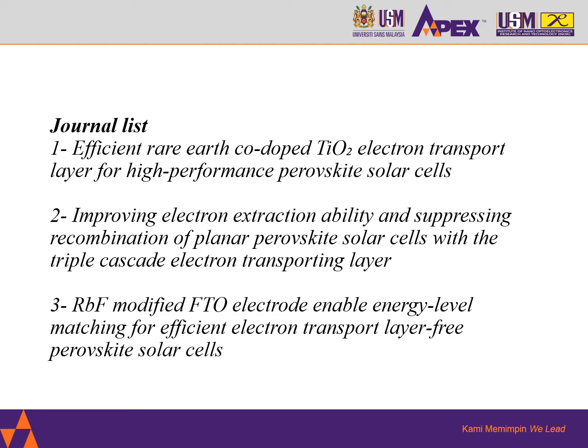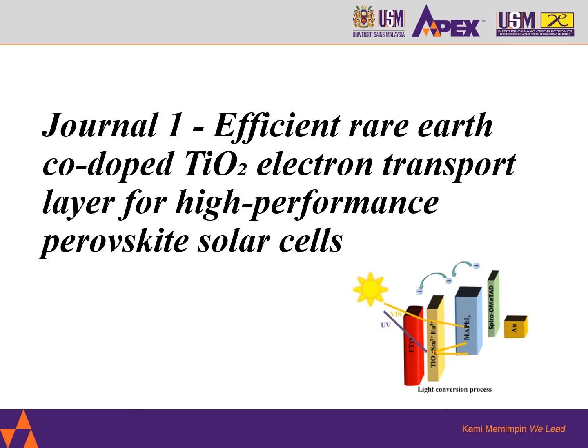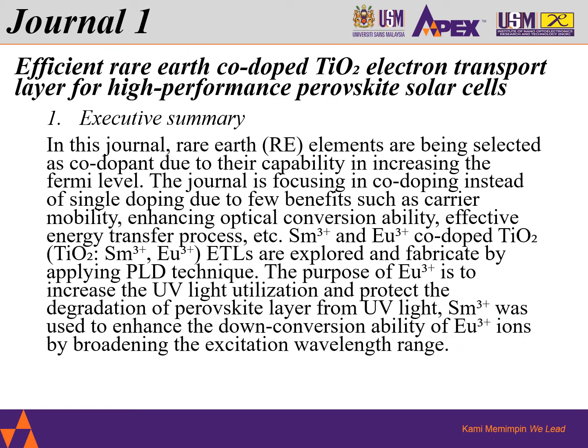For journal 1, this is the structure of how they carried out the samples. As you can see here, the FTO substrate is followed by TiO2, which is co-doped with Sm and Eu, then followed by the perovskite layer, HTL, and lastly the Au electrode. As a summary of the journal, the rare earth elements are selected as co-dopants because of their capability in increasing the Fermi level.